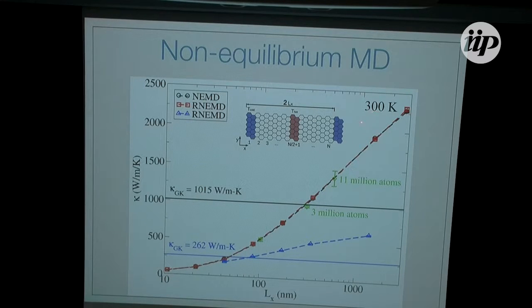And then we went up to higher temperature because we were doing everything at 300K. We wanted to do it at higher temperature, we went to 1,000K, and we got the same type of behavior. This is the equilibrium prediction, and this is the non-equilibrium prediction. So no matter what we did, the thermal conductivity really seemed to be scaling with the log of the system size.